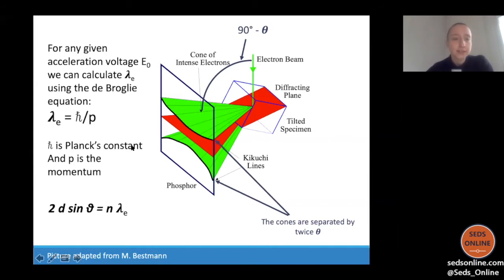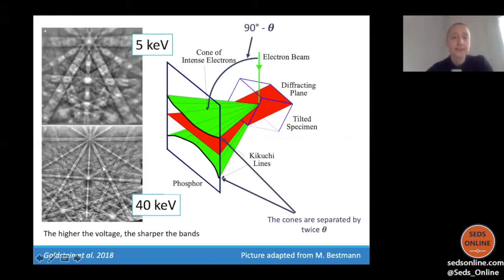And we can calculate the parameters of the crystal lattice using fairly simple equations. So we definitely have to know the wavelength, and the wavelength depends basically on your acceleration voltage. So for any given acceleration voltage, you can find out how to interpret your Kikuchi patterns in order to reconstruct the crystal lattice. And this is how they look. This is actually the same mineral at different acceleration voltages. This is from a very good textbook. If you would like to get into EBSD, I really recommend starting with Goldstein et al.